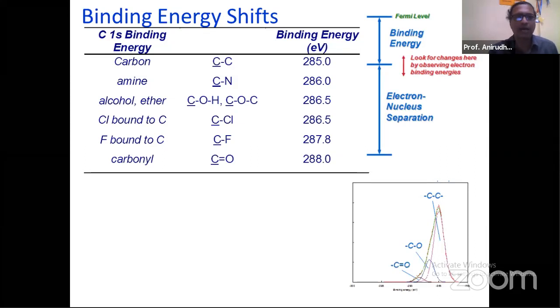Now, suppose you are looking at carbon. People have done enough investigation to find out that if you are looking at elemental carbon, that means it is in unbonded form, pure carbon, then the carbon 1s electrons correspond to a binding energy of 285.0 electron volts. So if you are suspecting carbon on your surface, when you do X-ray photoelectron spectroscopy, and you get a value close to 285, either 285 or some value in the neighborhood of it, you are more or less confirmed that there is carbon. And if those values are slightly different, then that is what I am going to explain next.